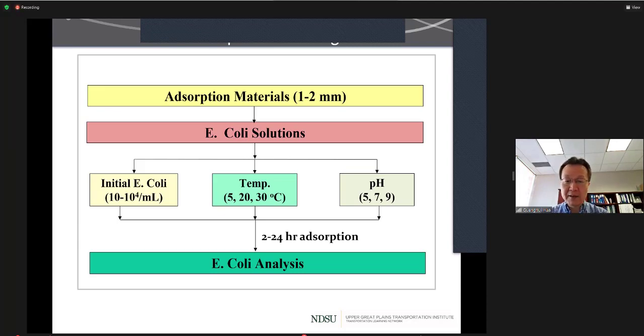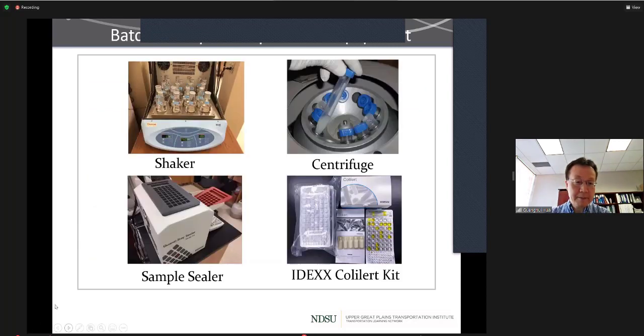And we performed the batch adsorption experiment from 2 to 24 hours to evaluate the impact of different contact times on the E. coli adsorption. So after the different batch adsorption experiments, we analyzed E. coli concentration after the treatment. Then we compared with the initial concentration to evaluate the removal efficiency. So these are the experimental equipment we used for the batch adsorption study.